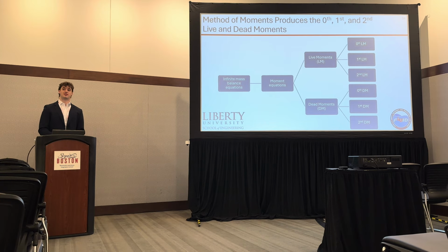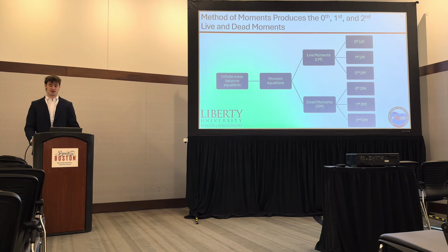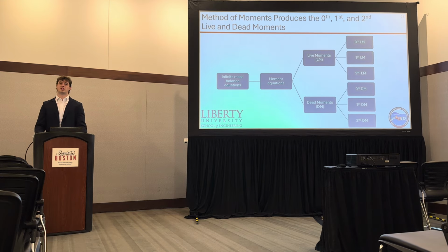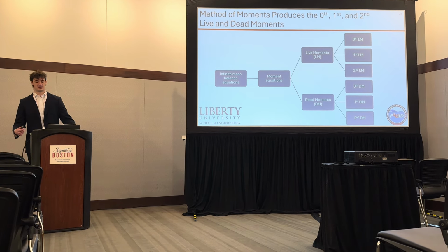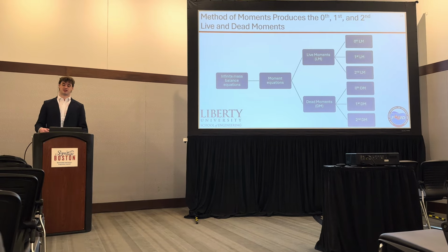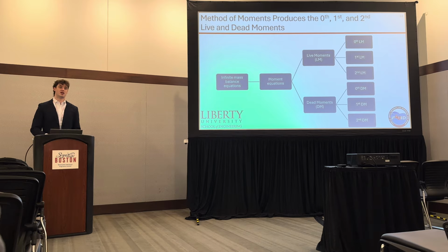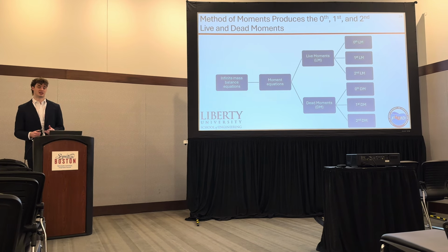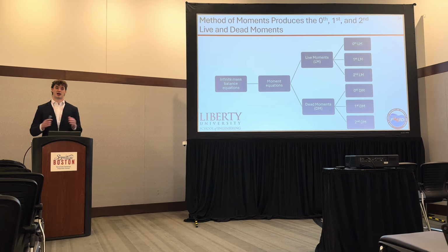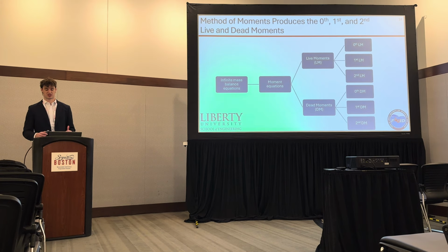A 0th moment gives information about how many entities are present, live or dead. The first moment provides data on the cumulative size, and for reactions like this, that would be similar to your molecular weight. And the second moment gives insight into the distribution breadth or variability to calculate metrics such as weight average molecular weight or polydispersity index. Polydispersity index, or PDI, being the breadth of a molecular weight distribution, and that is our main metric in this research.